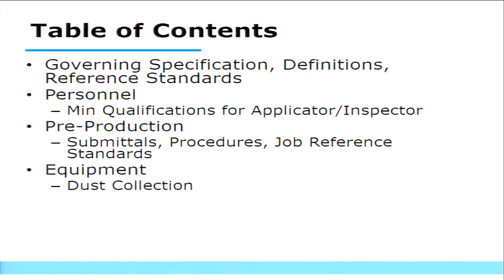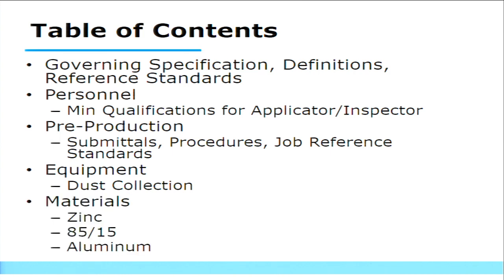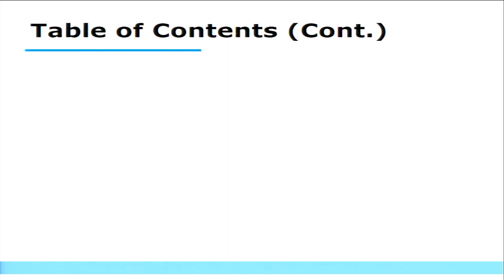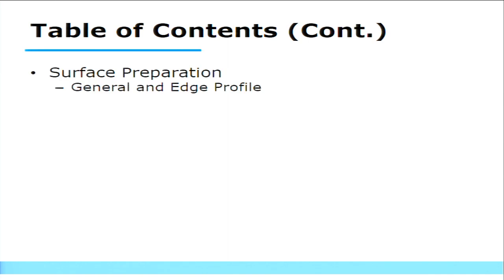Equipment, so the metalizing equipment itself, and we try to emphasize dust collection. Metalizing is a very dusty process. So we want to make that clear to everybody that it's very dusty and you need to think about that before you embark in doing a metallized project. The materials, so there's roughly three different materials that you can use. 99% zinc, 85-15, which is 85% zinc, 15% aluminum, and then 99% aluminum. There's also some others that exist internationally, but they aren't very prevalent in the US, so we don't really touch on those.